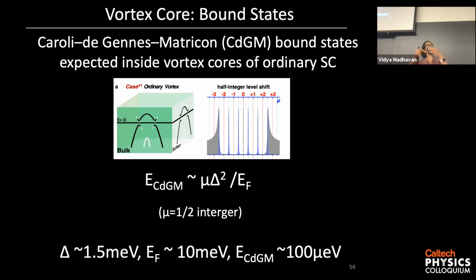And in fact, that's why you get these Majorana fermions at all. But remember, what you have is a little area inside a superconductor, right? Where these Bogoliubov quasiparticles are confined. So because of this confinement, you can have quantum well states made up of Bogoliubov quasiparticles. And these are called Caroli-de Gennes states. So in any type 2 superconductor, if you turn on a magnetic field and you look inside the vortex core, you'll get these Caroli-de Gennes states that are actually peaks in the density of states. So these are not Majorana fermions, these are just trivial bound states inside the vortex core.